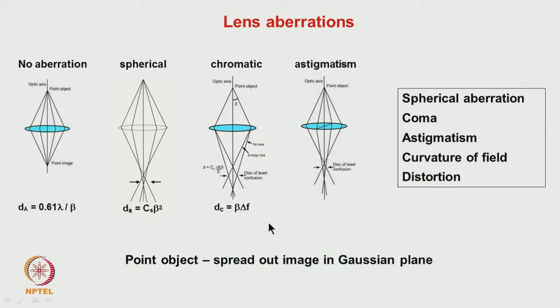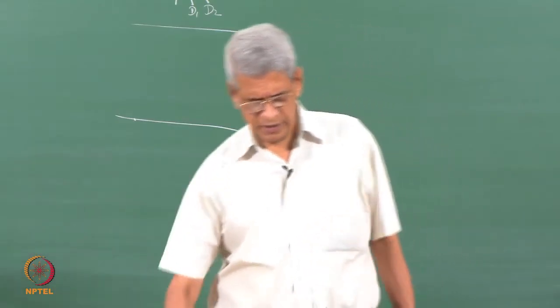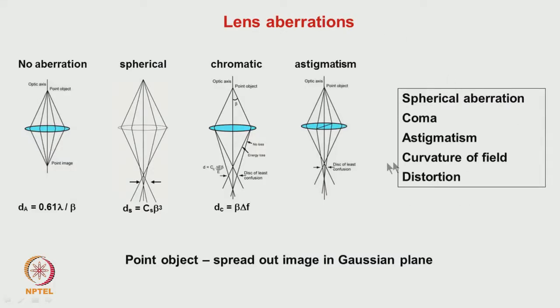But what is the reality in a microscope? The lenses have aberrations. In an ideal lens there is no aberration and a point object gives a point image. Spherical aberration, chromatic aberration, and astigmatism all cause a spread in the intensity from the optic axis outward, so point-to-point resolution is degraded considerably.